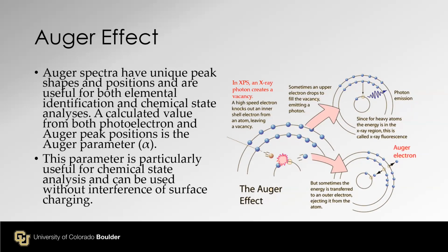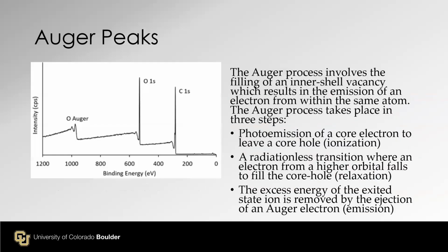In the Auger process, it can happen, okay. It's the same for the next step. The energy with a slightly higher level can fill in here, and instead of emitting photons, an electron from a different, or could be the same, shell can be emitted as an Auger electron. Okay. This is no photon emission, so it is a radiation-less process. This is Auger.